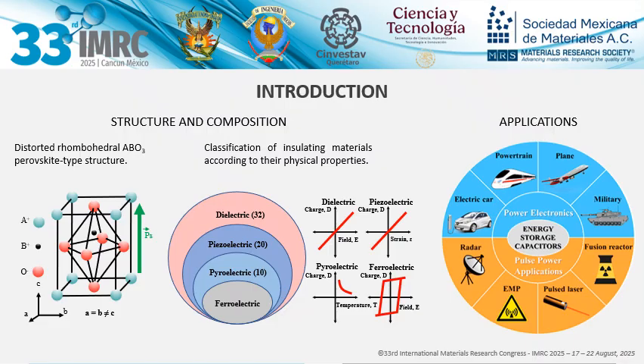Due to these properties, ferroelectric materials have applications in pressure or temperature sensors, ultrasonic actuators, non-volatile memory devices, energy harvesters, and microelectromechanical systems. However, pure bismuth ferrite presents some important challenges: the formation of undesired secondary phases such as mullite and sillenite during synthesis, and issues like low density or high leakage currents, which limit its performance.